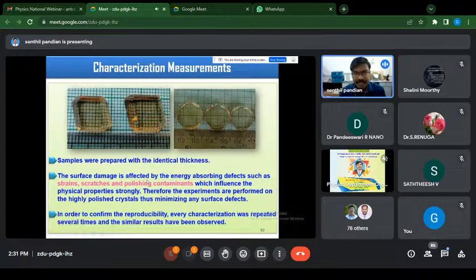The surface damage is affected by energy absorbing defects such as strains, scratches, and polishing contaminants, which strongly influence the physical properties. Therefore, all the characterization measurements were repeated several times on highly polished crystals, thus minimizing any surface defects. In order to confirm the reproducibility, all the characterizations were repeated, and more or less similar results have been observed for the SCST and SR method grown crystals.